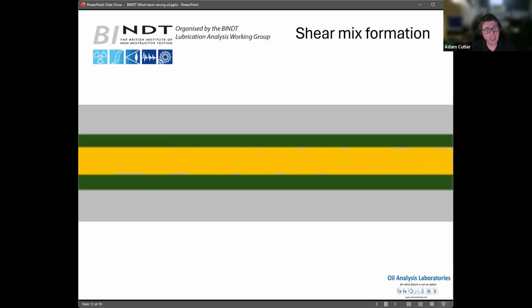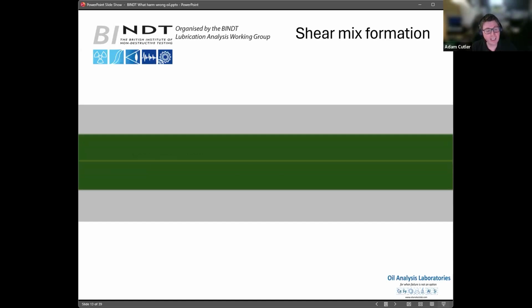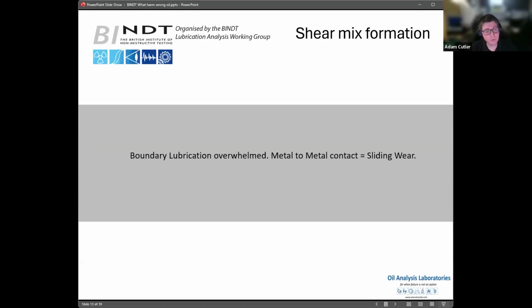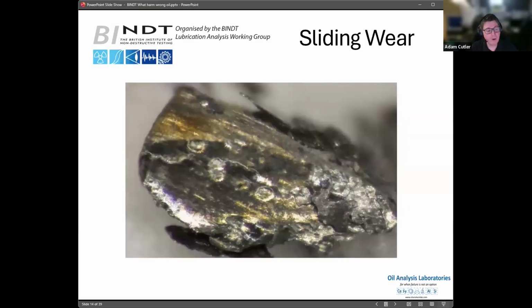These then deposit and react with lubricant additives and form what's called a shear mix layer, or boundary lubrication. Under normal circumstances, you have the full fluid thickness, so the oil is separating the components. But under reasonable load, but not overloading, you can have it where the surface actually comes into contact just from the additives itself. If you take this too far, you can get metal-to-metal contact, which is abnormal wear. So boundary lubrication is typically normal wear, but if you overwhelm that, you get abnormal wear. If you get to abnormal wear from metal-to-metal contact, you lead to sliding wear.